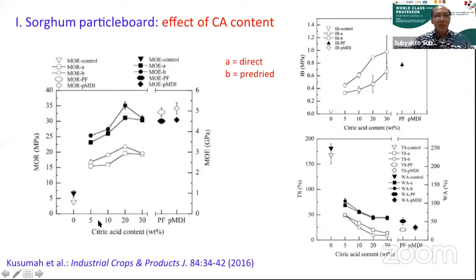citric acid content, and we have two methods here. Direct is we spray directly onto the particles and then directly hot press. Pre-dry is we pre-dry the particles for about 15 hours at 80 degrees C, and then we press. And the results show that the direct application has lower properties compared to the pre-dry. And we can also see here that citric acid content of 20% has the highest mechanical strength. This is the internal bond strength, also the lowest thickness swelling.